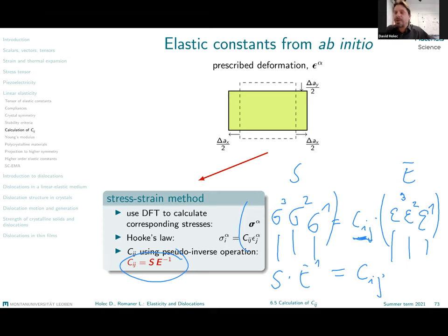Obviously, what you can do is that you can apply 100 deformations, get 100 stresses. You have, in fact, 600 equations that determine the components of this Cij matrix. You overdetermine your problem. You have too many equations. In ideal case, those would be linearly dependent. In practice, when you do the calculations, they will not be. They will not be because of accumulation of numerical errors or because your material that you're describing is truly nonlinear in the regime. If I double the strain here, I should get twice as large stress here.